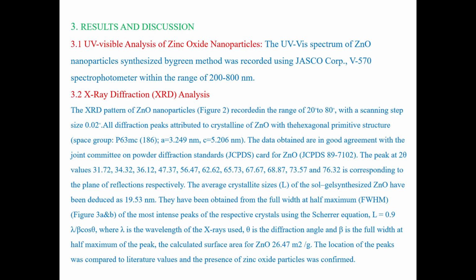The average crystalline size of the sol-gel synthesized zinc oxide has been calculated as 19.53 nanometer. It has been obtained from the full width at half maximum, as in figures A and B below. The most intense peak of the crystal is used in the Scherrer equation, that is L is equal to 0.9 lambda upon beta cos theta, where lambda is the wavelength of the X-rays used, theta is the diffraction angle, and beta is the full width at half maximum of the peak.